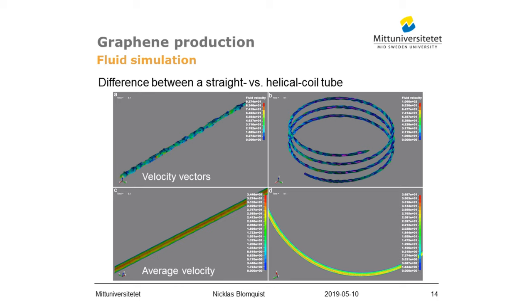We can also see from this helical coil shaped tube that we have a swirling effect. It looks like the fluid is rotating when it travels in the tube. From the lower images, we can see that the straight tube has a high speed region in the center. But in the helical coil shaped tube, the high speed region is shifted outwards towards the tube wall. So we can see from this that we had a difference between these two geometries. And maybe that makes a difference on the particle also.